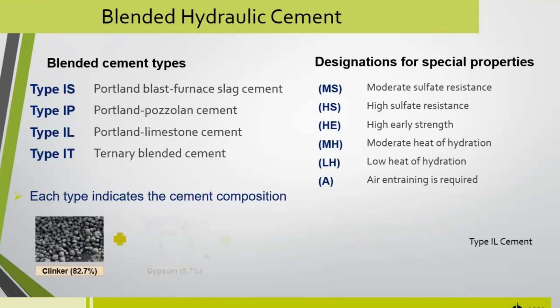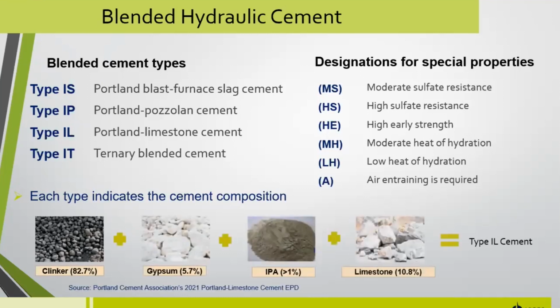So let's take a look at the composition of this real quick. So this is a type IL cement. Now we're at just under 83% clinker, 5.7% gypsum, process addition, and then the target, in this case, the average limestone content of 10.8%.